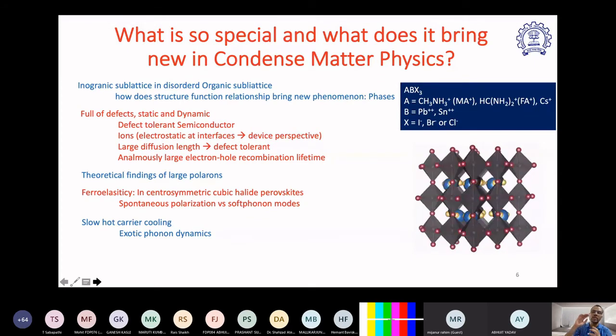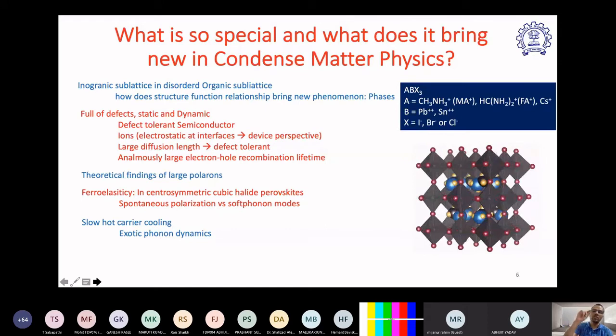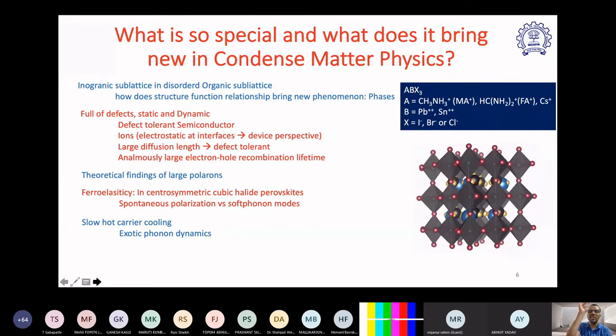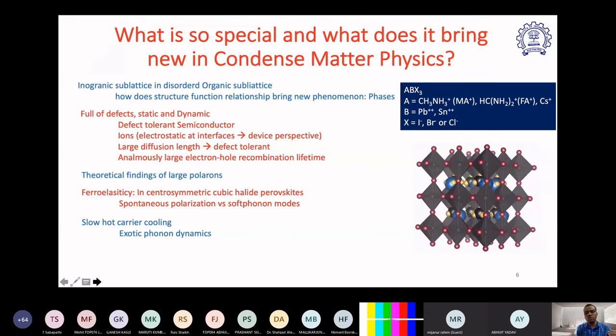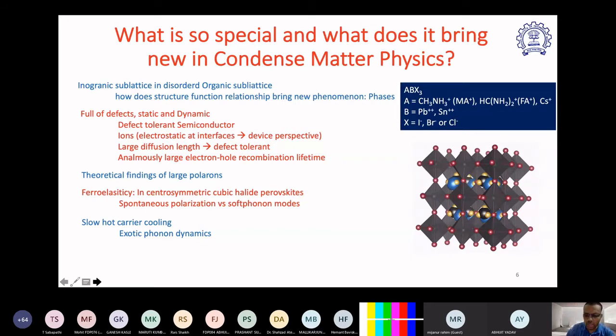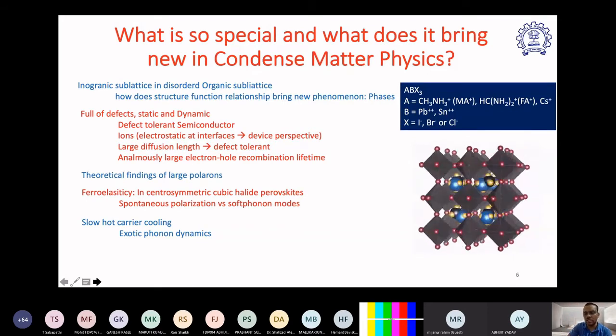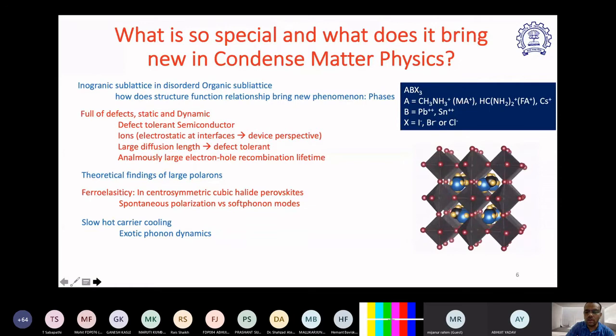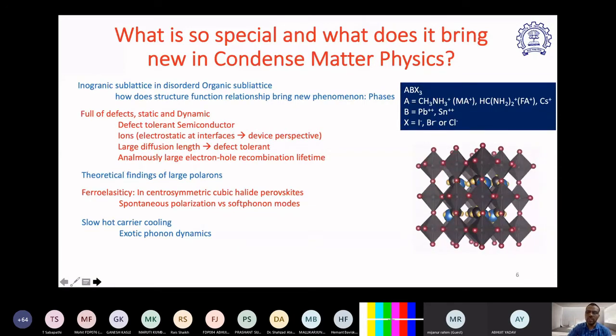And what happens to that extra energy? Once the charge carrier goes to that higher, hot state of the conduction band, it relaxes back by releasing the energy to the phonons. It gives the energy to the moving lattice, the lattice gets a little bit hot, and the carrier falls down to the minimum of the conduction band. Then you see the emission related to the band gap of the semiconductor, or photocurrent.